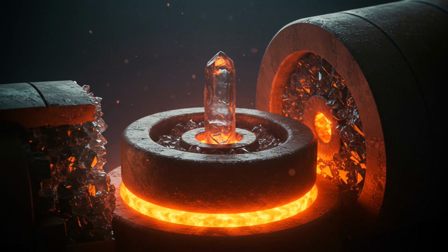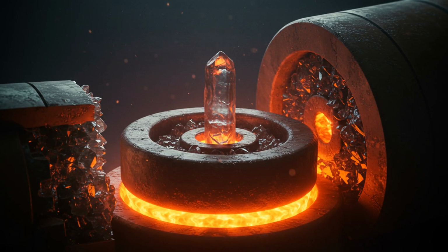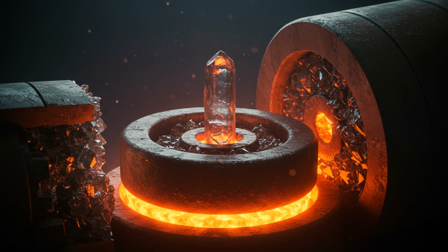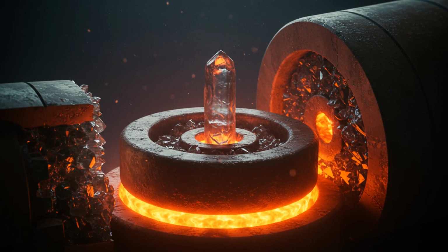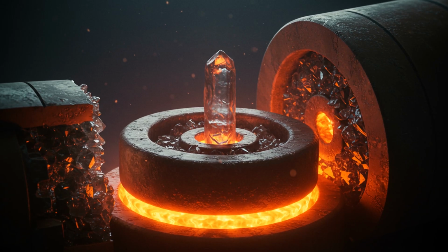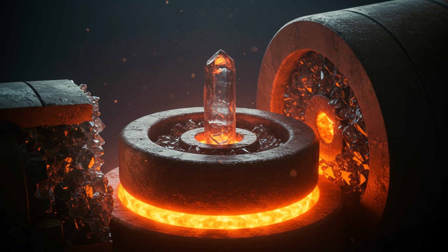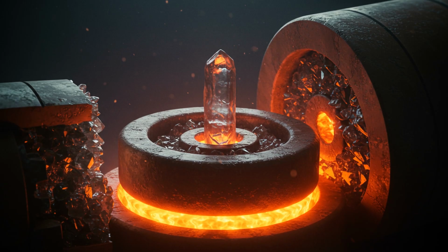The turbine blades are the most stressed components in the engine, and their strength comes from a process called single crystal casting. In a normal piece of metal, there are millions of microscopic boundaries between individual crystals, called grain boundaries. Under high heat, these boundaries act like cracks, allowing the metal to stretch and eventually snap. To solve this, engineers grow the entire blade as one single continuous crystal. The molten superalloy is poured into a ceramic mold inside a vacuum furnace.